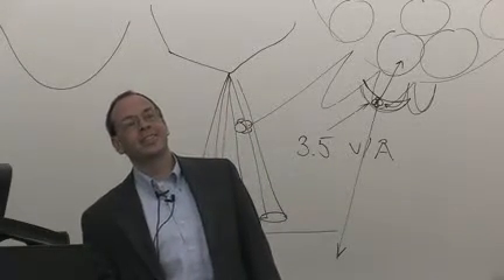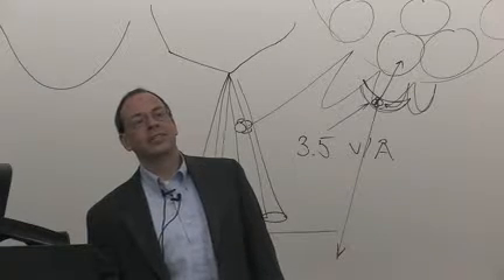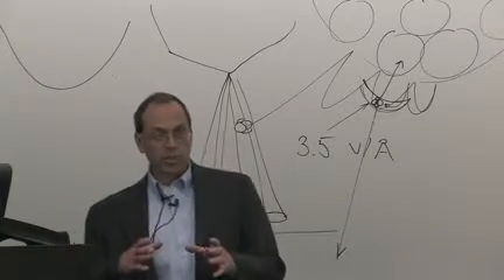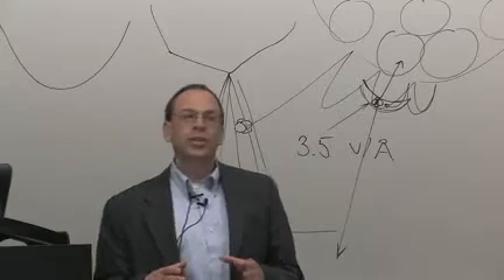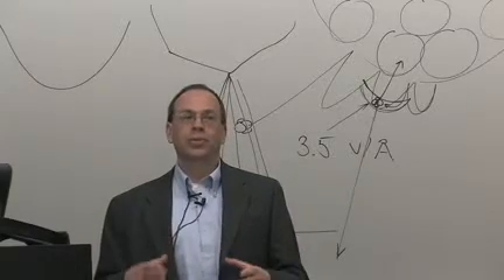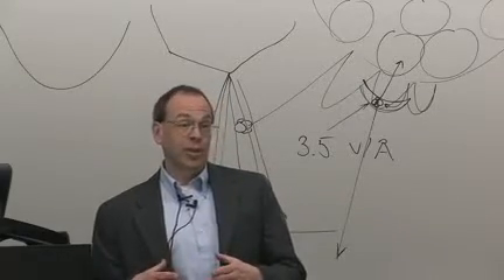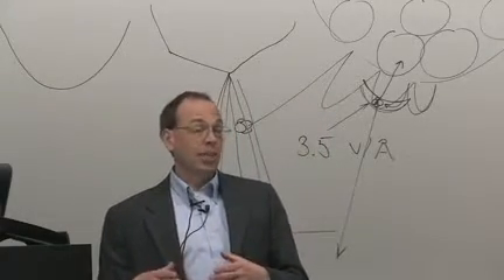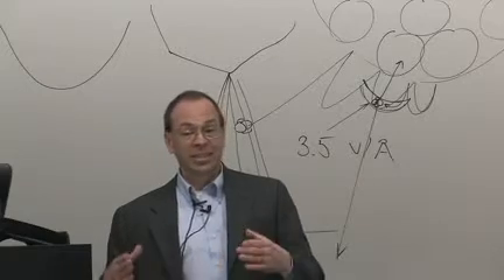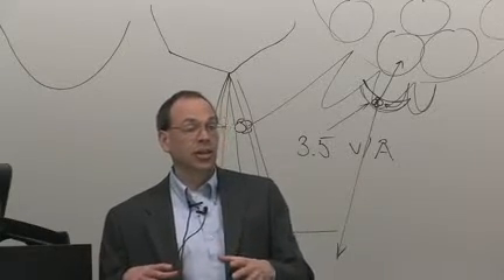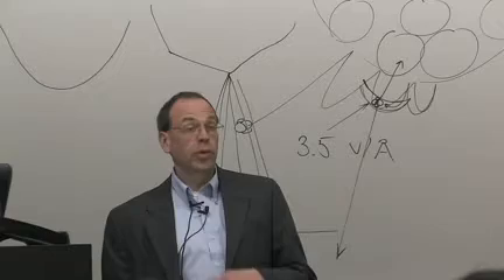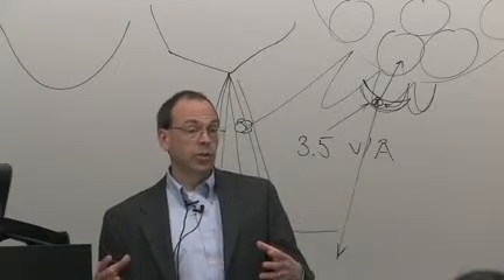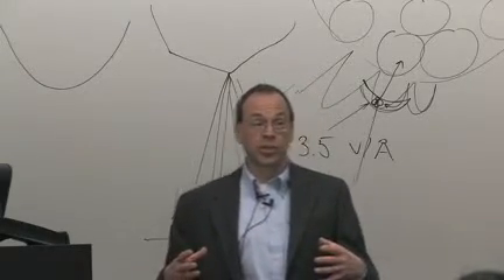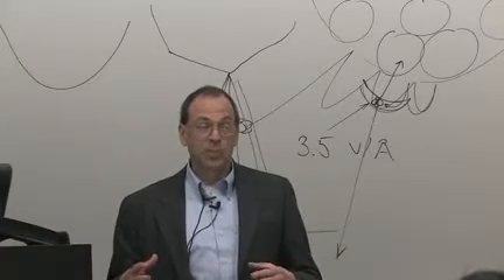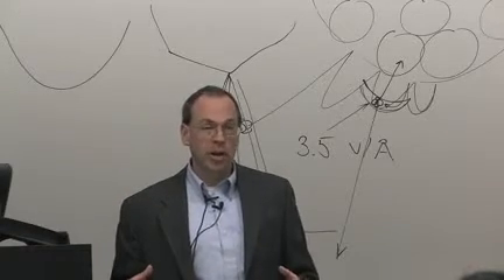Can one change the temperature in the ultra-high vacuum chamber, the sample's temperature? We've only done experiments. As a commercial product, we don't. But our curious people back in the factory found a way to heat the sample, and that was really terrific for outgassing and removing that adsorbed layer of stuff. We've also tried cooling it. That helps a lot in reducing the mobility of the hydrocarbons on the surface. So we did some rough experimentation. It's not part of the product.